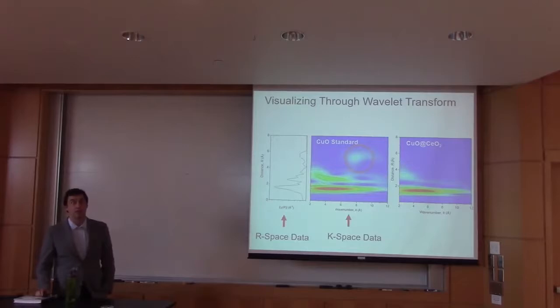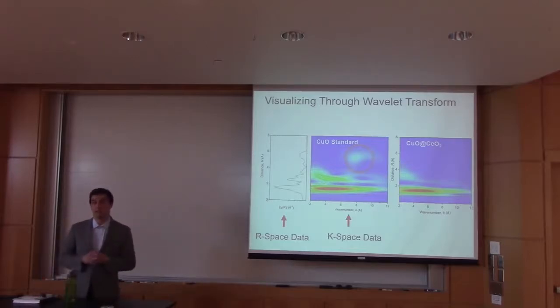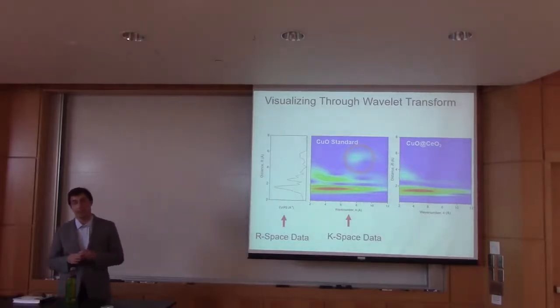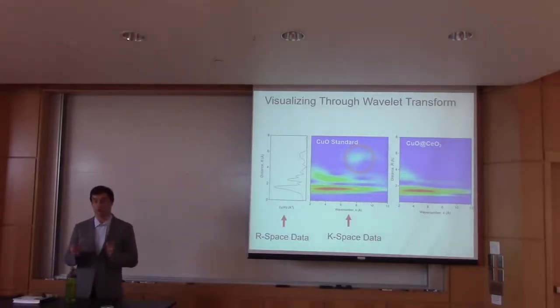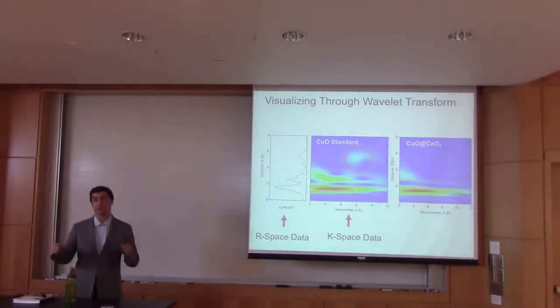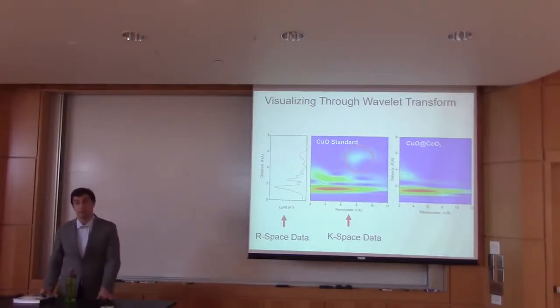Yeah, so in this sample, we're looking at basically the crystal size of that copper oxide. And what will often happen is we'll form large crystals, which is what is decreasing the efficiency of this reaction. So we're still forming those crystals, we're just trying to make them as small as possible. So we're still seeing the crystalline structure of this, and the copper oxygen scattering distance is going to be the same in that crystal. We're just trying to make it small enough that we don't have that copper-copper distance. I see, so it's just about distances between things, not about the presence of them or not. Yeah, it's maintaining size.